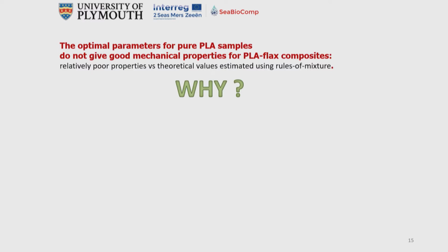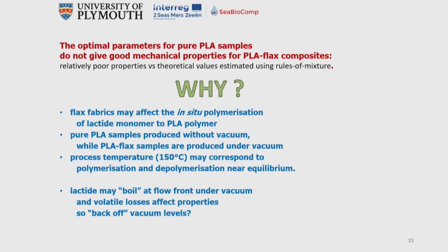The optimal parameters don't give the best mechanical properties. Why? Well, the flax fabrics may affect the in situ polymerization of the lactide monomer. At the temperatures we're working at, the fibre should be dry, but maybe there is some residual moisture.